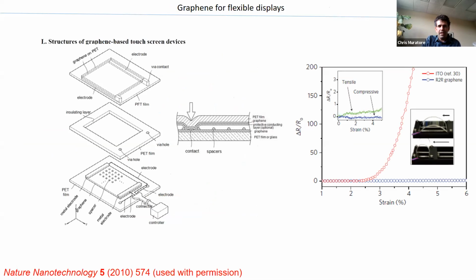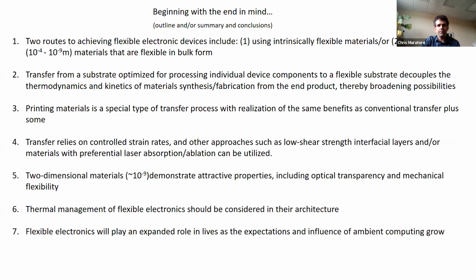This is more of the same, just the change in resistance as a function of strain. And it depends what kind of strain you've got. Compressive strain tends to push the atoms together, where tensile strain tends to pull them apart. And if we have a large area, like a big graphene display, we're going to have lots of defects, and a tensile stress is going to pull the material apart at those defects.